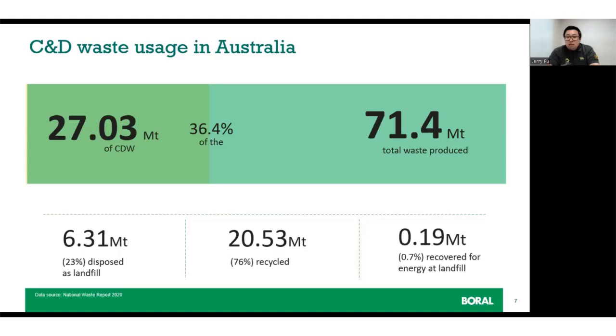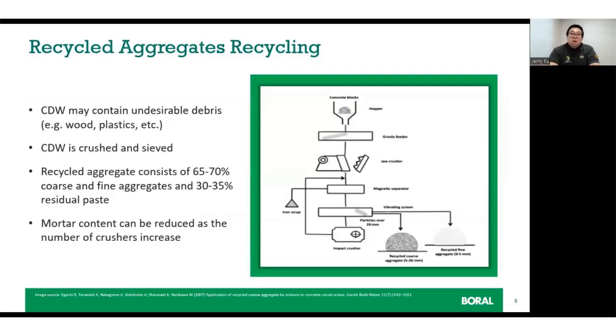According to the 2020 National Waste Report, Australia produced about 27 megatons of C&D waste, which is about 36% of the total waste we produce. 23% of the waste was disposed of either as landfill or destroyed, 76% was recycled, and 0.7% was recovered for energy at the landfills. Usually after demolition of old roads and buildings, the removed concrete is often considered worthless and disposed of as demolition waste. By collecting the used concrete and breaking it up, recycled concrete aggregates are created.